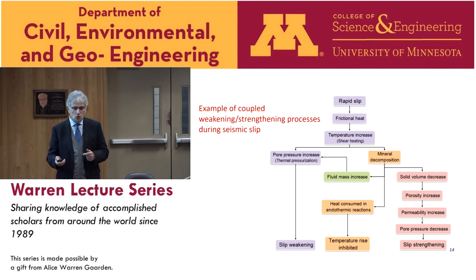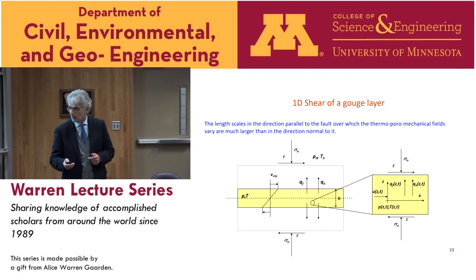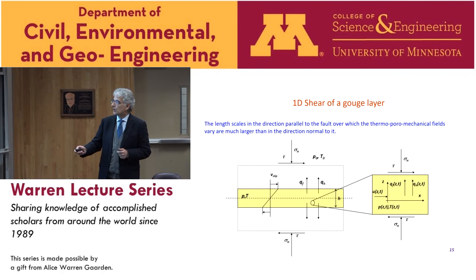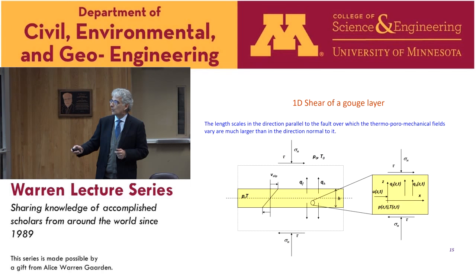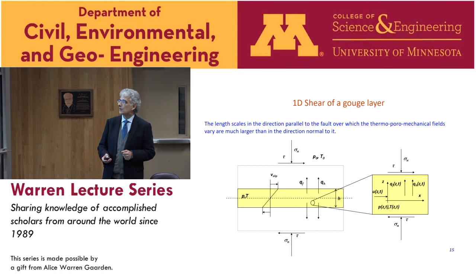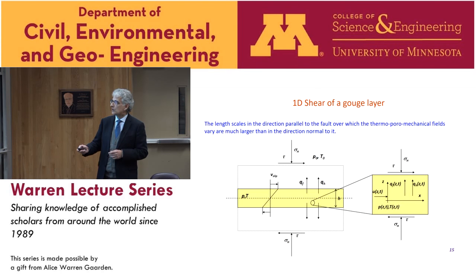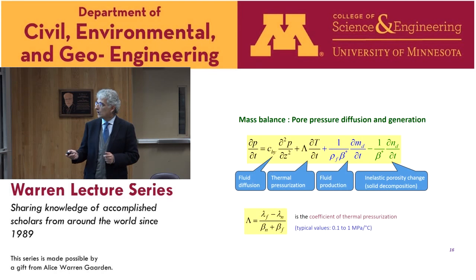So I would like to show an example of a simple modeling. So we take here a layer under an imposed slip at a typical seismic slip rate of about 1 meter per second. The layer is long enough so that we can assume that the length scales in the direction parallel to the fault, over which the thermo-poro-mechanical fields vary, are much larger than in the direction normal to it. So we can consider the variation only in the direction z, which is normal to the fault, and with time. And the governing equations are the following.